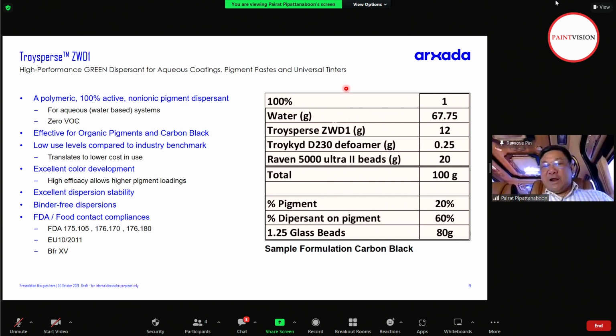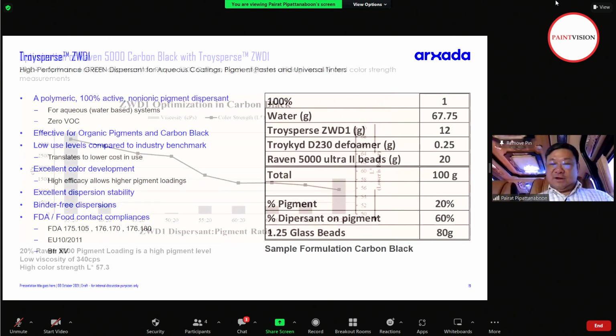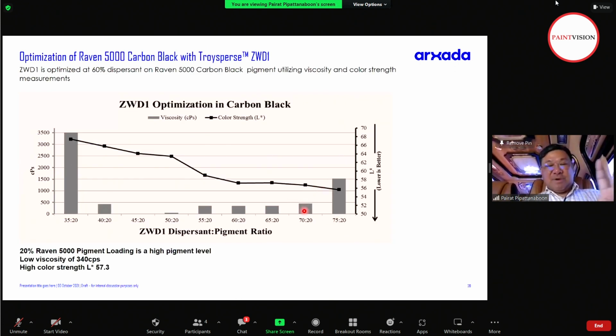This is just a guide formulation that we tested in the lab for 20% carbon black loading, which is quite a high loading, using Raven 5000 Ultra 2 from Birla. And the percent on pigment weight is 60% to stabilize that. We came to this from a study where we tried many formulations. The number in front of each bar means the first number is the percent on pigment weight.